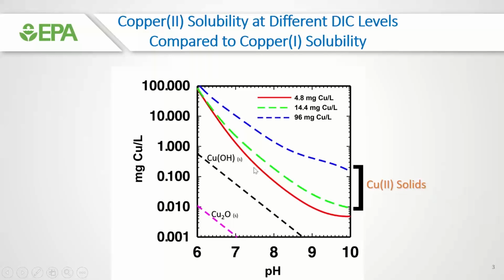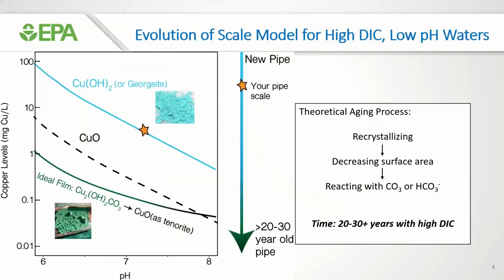And that's not to say copper 1 chemistry isn't important, because we always do find copper 1 minerals on copper pipes. And there are cases that we've been involved with historically, let's say low DO groundwaters that are not adding disinfectant, and then they switch to adding disinfection. So they shift the copper chemistry on the pipes from copper 1 to copper 2, and then they have a big problem. So we have certainly run across that, and it's something to be aware of, but generally we consider copper 2 chemistry as being most important.